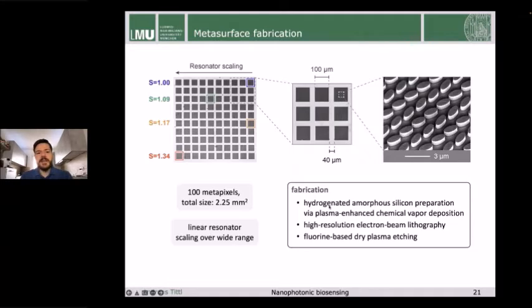So we fabricated this in our clean room using electron beam lithography, and this is the full metasurface that we created, which consists of 100 metapixels. The total size of this is a little bit above 2 square millimeters, so it is a macroscopic kind of object. And again, as I mentioned, it consists of these 100 by 100 micron metapixels, which are spaced by roughly 40 micron. And this is just a scanning electron microscopy image here to the right, showing you that these structures are really nicely reproduced in the fabrication.